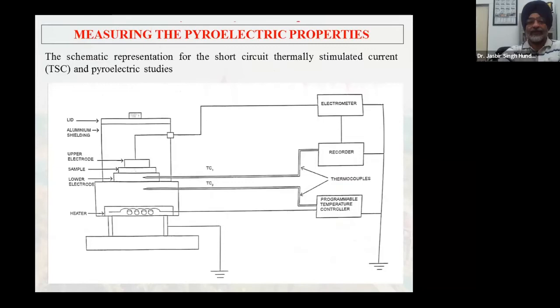So this was the setup used for studying pyroelectric studies as well as thermally stimulated current studies. I'll just explain what these are. Here again, this is a base, and this is a heater embedded in it. We have two thermocouples, TC1 and TC2, measuring the temperature of the heater and that of the lower electrode. The sample is placed here, and the upper electrode is placed here. In fact, we use brass electrodes here. Of course, aluminum electrodes were coated on the films, but they were placed in between. This was a brass substrate, the sample was placed here, and then the electrode here. So when you heat the film, because of the motion of dipoles within the film, there is a change in the surface charge and there is a flow of current in the circuit. You can use that for thermally stimulated current studies. You can also use the same setup for pyroelectric studies.